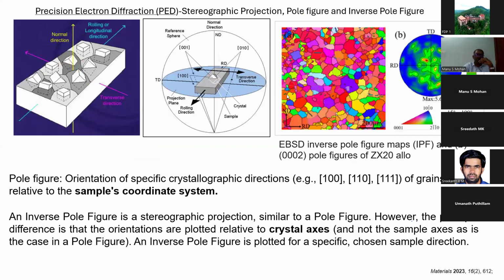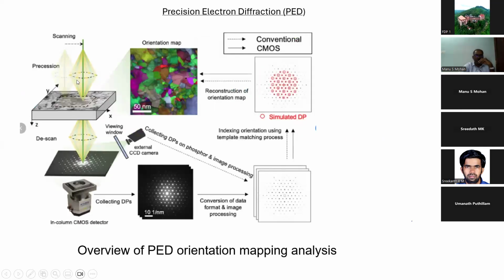Before going to my result, I want to say a few things about how texture and orientation are represented. So this is the equipment. You get an orientation map. Basically, you have a specimen. You tilt the electron beam using the beam deflection coils, and then using image deflection coils again you align the beam at the center of the diffraction pattern.